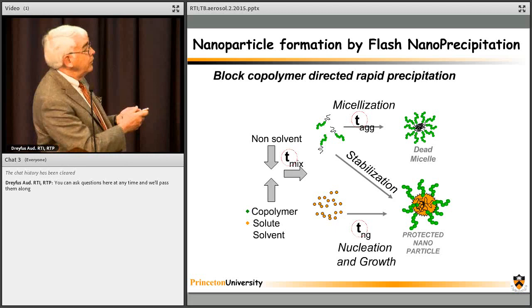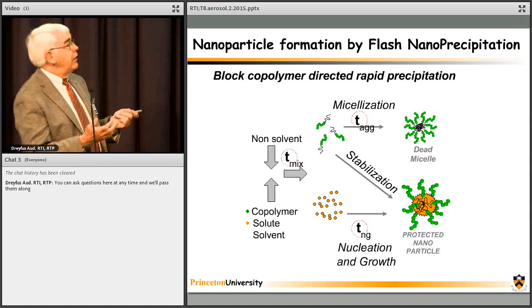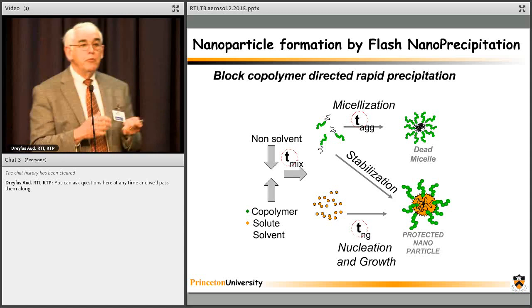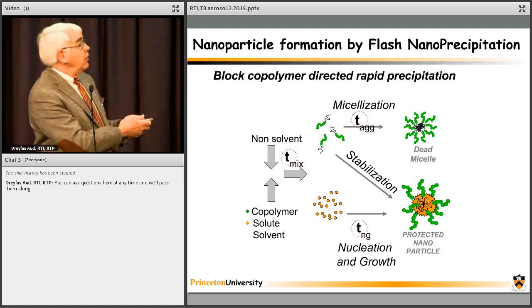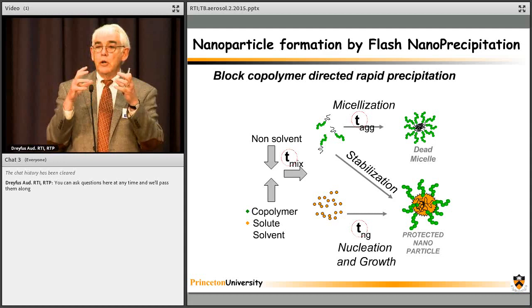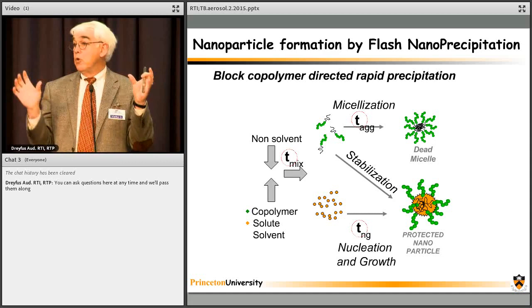What's coming out is this now essentially aqueous mixture, which has in it the hydrophobic solutes, the block copolymer. I've separated them in space, but of course they're intimately mixed in space. They're diffusing around. It's sticking to the first thing it sees. So the hydrophobic solute components are aggregating into larger and larger objects. The block copolymer is absorbing on those objects as they diffuse around. The polymer chains are also hitting each other and fusing and making micelles, polymeric micelles.